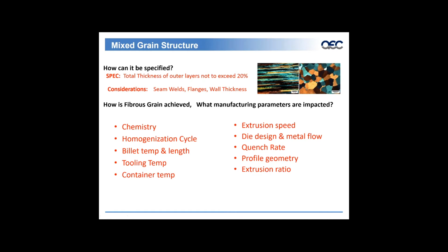How is fibrous grain achieved? What manufacturing parameters are impacted? You'll see here primarily a lot of it has to do with time and temperature, but chemistry, as we spoke before, of our raw material, the homogenization process and cycle associated with that raw material that's provided to the extrusion press, the billet temp and length itself, so the temperature of the raw material that is loaded into the extrusion press is critical, the temperature of the tooling, the container temp in which the billet resides during the extrusion process itself, the speed in which the extrusion occurs, die design and metal flow, the quench rate, profile geometry, and extrusion ratio. So a lot of process parameters are involved in the creation of a fibrous grain.